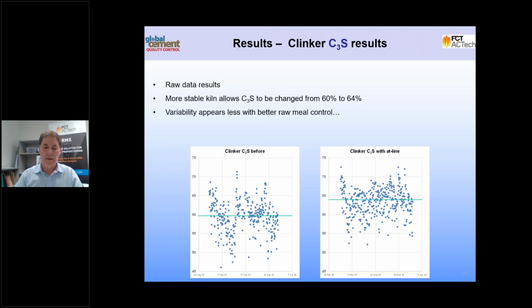So I've got some results here of the clinker. The graph on the left shows about a month's worth of results of clinker before the automatic control system was put in place, and then another month's worth of data afterwards. So the plant has been able to make use of this reduced variability because the kiln has been much more stable. And as a consequence, they've been able to increase their C3S target from 60% up to about 64%. They wanted to do that so they could get some additional cement strength gain. This is something they weren't able to do previously because of stability reasons with the kiln.